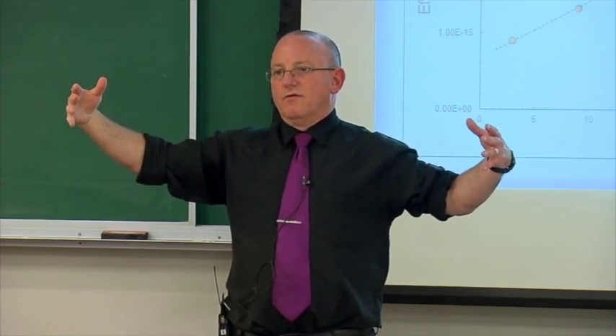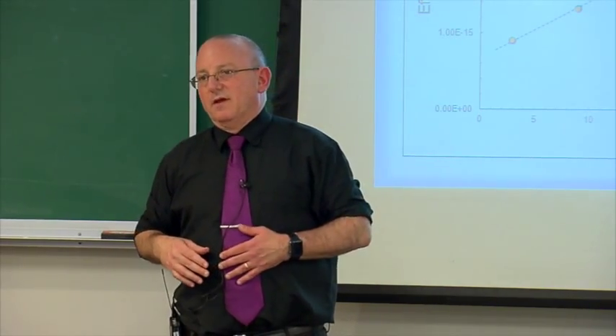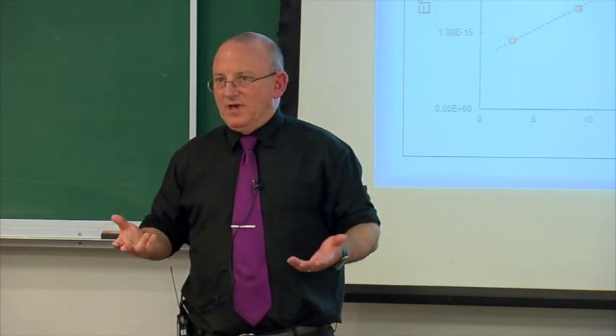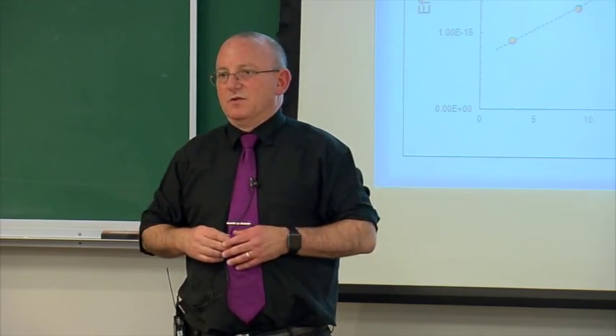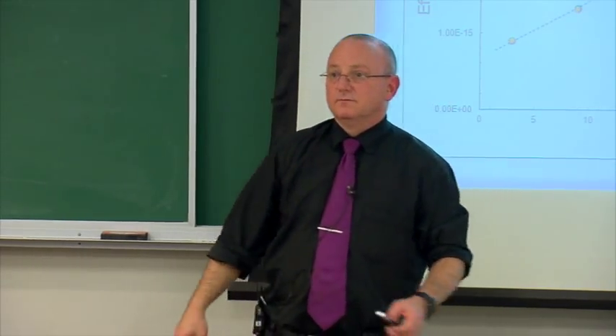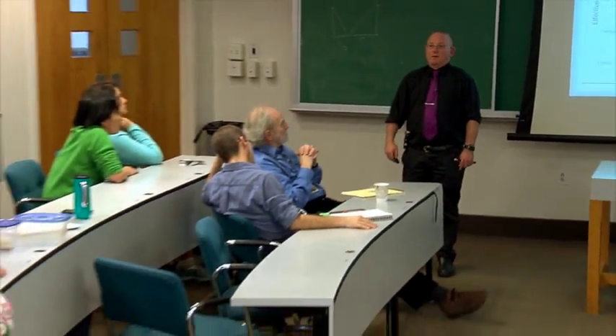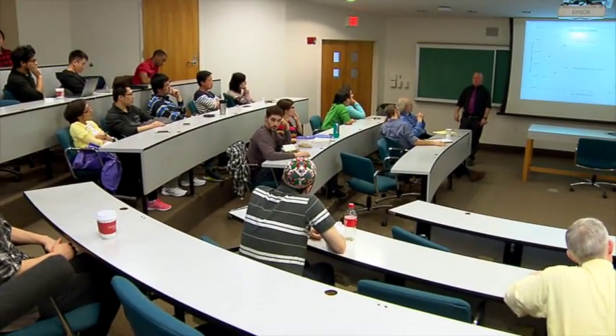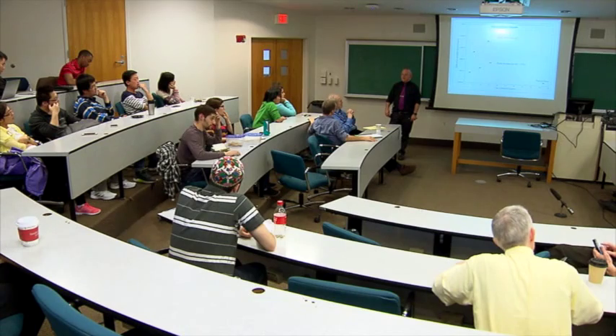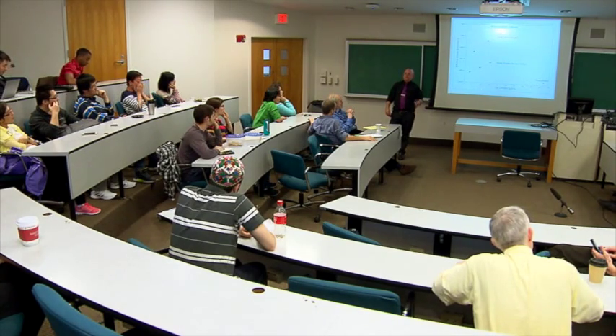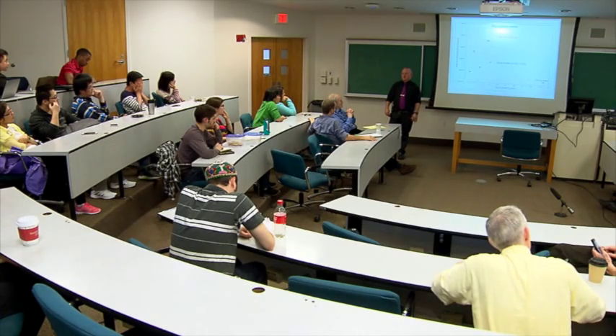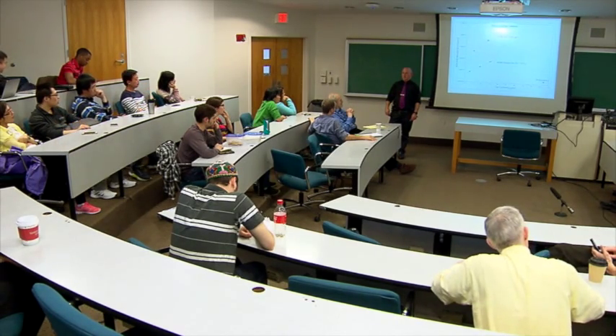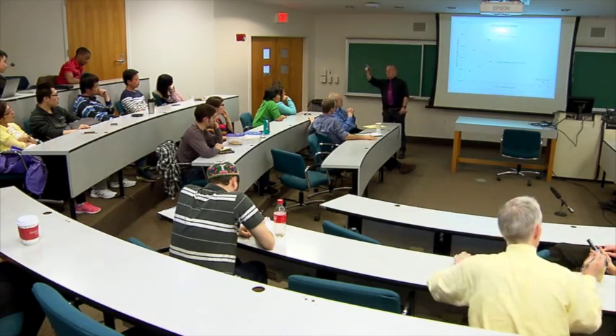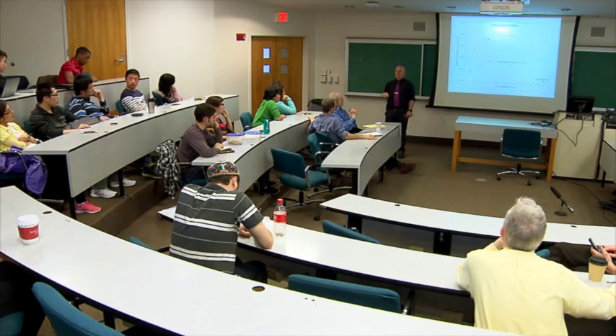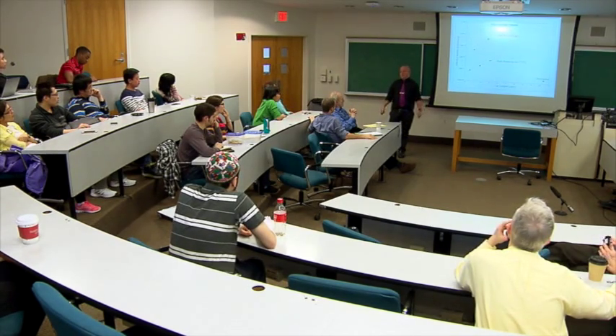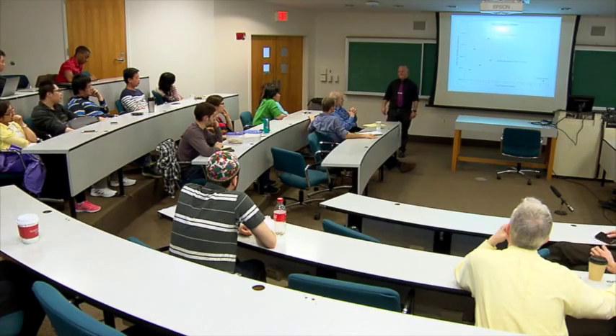Once you get elongated grain growth, abnormal grain growth, then this parabolic type of fit just doesn't work. So we have to look at the aspect ratio as a function of time and not just the grain size in order to do kinetics. Change point phenomena is due to the mismatch between the growth rates, but not anything inherent because of the calcium. It's because of the calcium that not only does it grow faster, it becomes anisotropic, and this type of kinetics analysis doesn't work when it's anisotropic. So we stayed until it rolled over. The rolled over point is when it goes anisotropic. We could have fit it out there. It's just, in my opinion, that the numbers would have been incorrect. Okay?